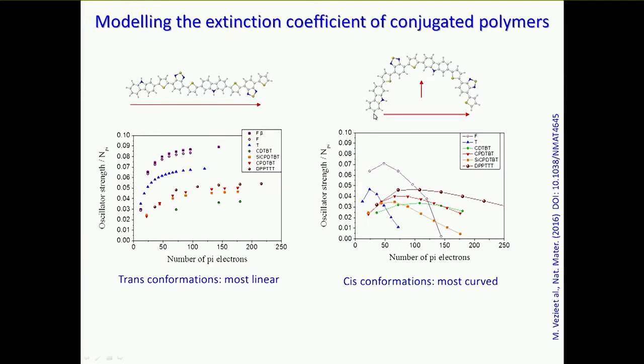So depending upon the collinearity of the polymer, what is the angle of deviation between one monomer and the next, the degree of bending as you make the chain longer will change. So what's happening? If we have the chain as long as it can possibly be, that's going to maximize the transition dipole moment of the first transition, which will generally be aligned along the polymer chain. That would be maximized for the most linear configuration, in this case the trans configuration of monomers. If our chain becomes somewhat bent, the transition dipole moment of the first transition will be weaker, and it will tend to give up some oscillator strength to higher lying transitions that would, in the linear configuration, be symmetry forbidden. So we could see some oscillator strength being passed from the first transition to higher transitions, and we see this in the calculations.